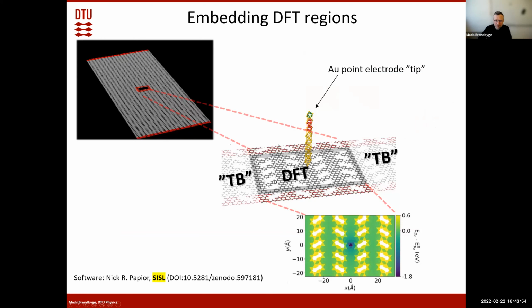And that means that we can actually take a structure like this and take a part of the structure and treat that with DFT. So we could, for instance, put a one-dimensional point contact, all calculated with DFT, and inject current from that into, let's say, one of these ribbons here. All this region here is then treated by DFT, and then it's surrounded by tight binding. And then we can see how the current that we inject from this tip is propagating into this material.